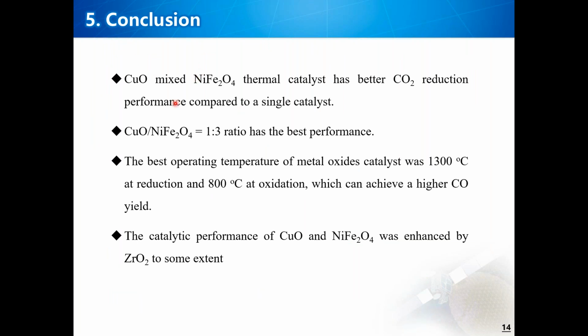In conclusion, CuO mixed nickel ferrite thermal catalyst has better CO2 reduction performance compared to a single catalyst, and CuO plus nickel ferrite equal to 1 to 3 has the best performance. The best oxidation temperature is 800, and reduction temperature was 1300. And the catalytic performance of CuO and nickel ferrite was enhanced by zirconia to some extent. And then we will use this catalyst to do electrochemical tests. And that's all.